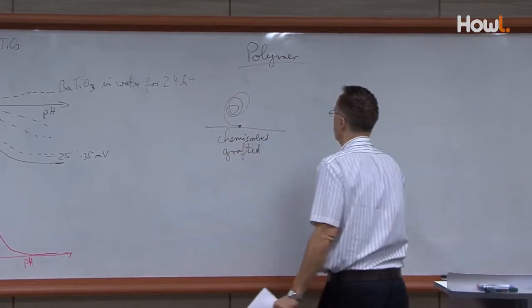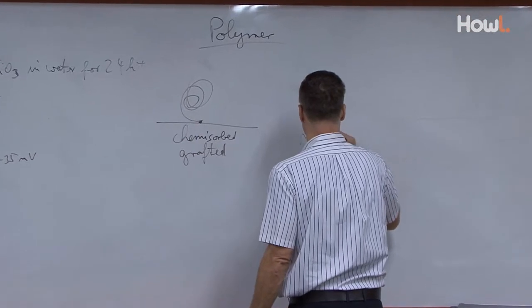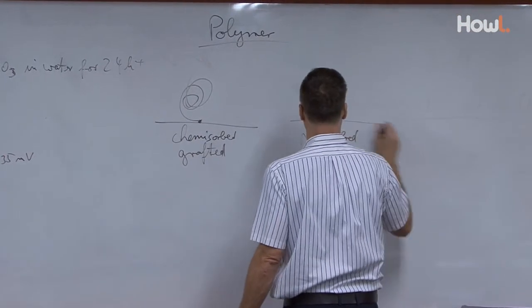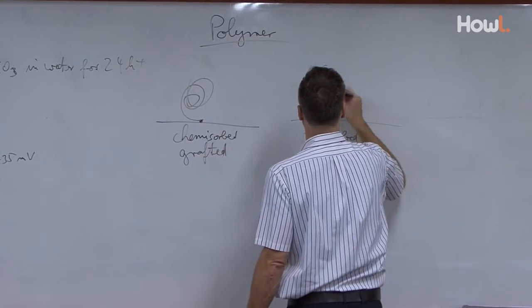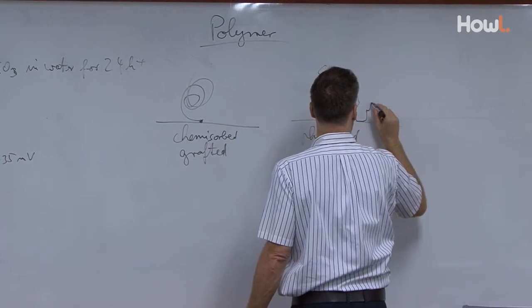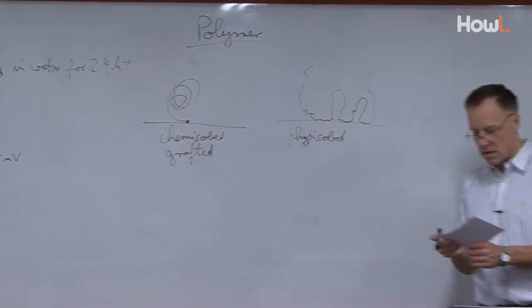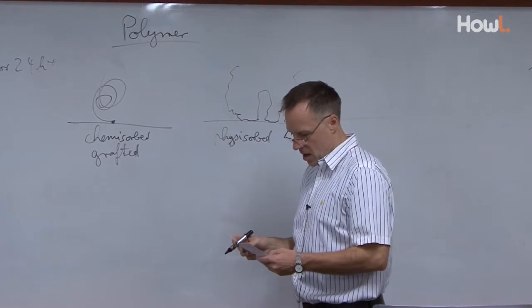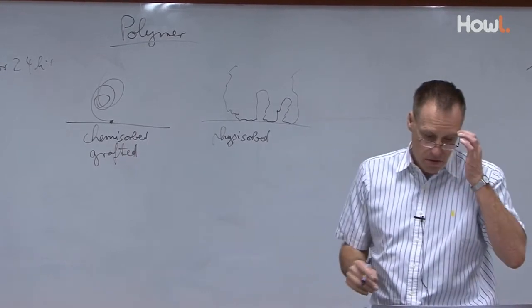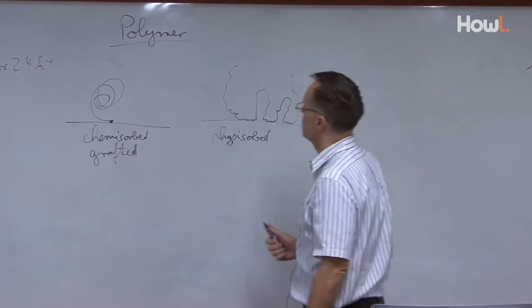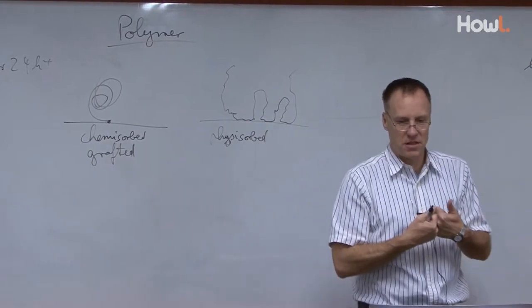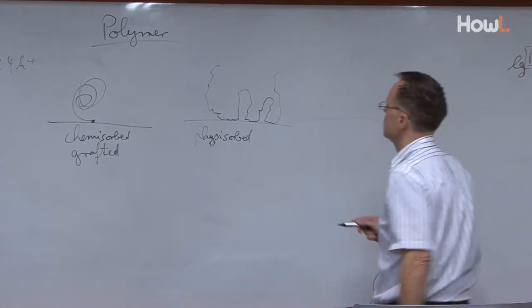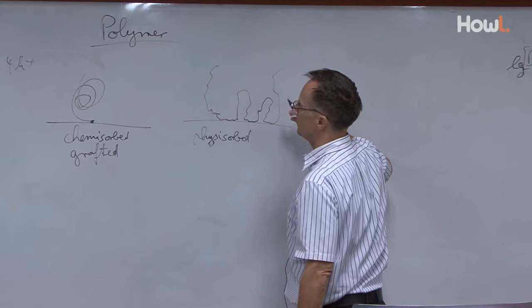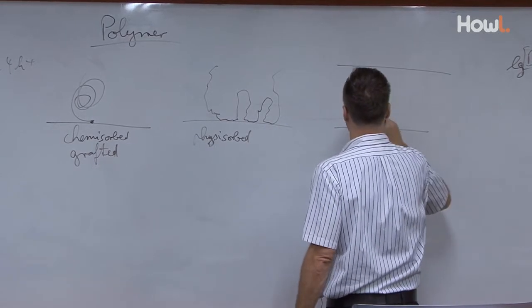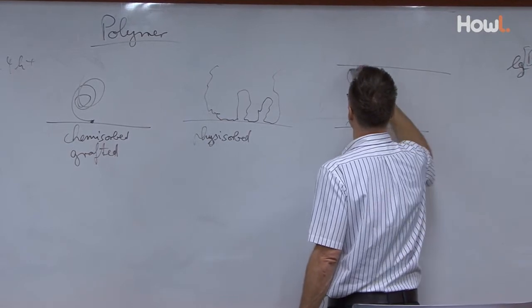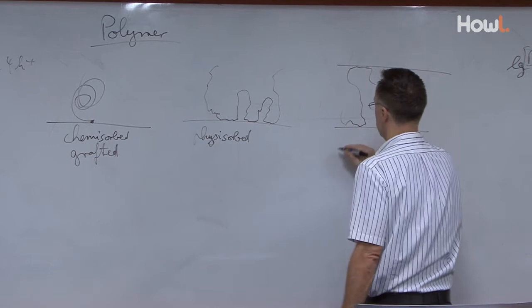There's another possibility, and that would be the physisorbed, and that's the much easier one. And physisorbed typically does this. So it has some chain ends that don't adsorb, something that adsorbs, some loops forming, something adsorbs, some loop, and another chain end. Yeah? So this will be physisorbed. And now there is, of course, the possibility when you have two surfaces approaching that you have different types of interactions. Let's do this when you have two surfaces. You can have then either a so-called, let's say here, physisorption and bridging phenomenon. Yeah, so it would be bridging.